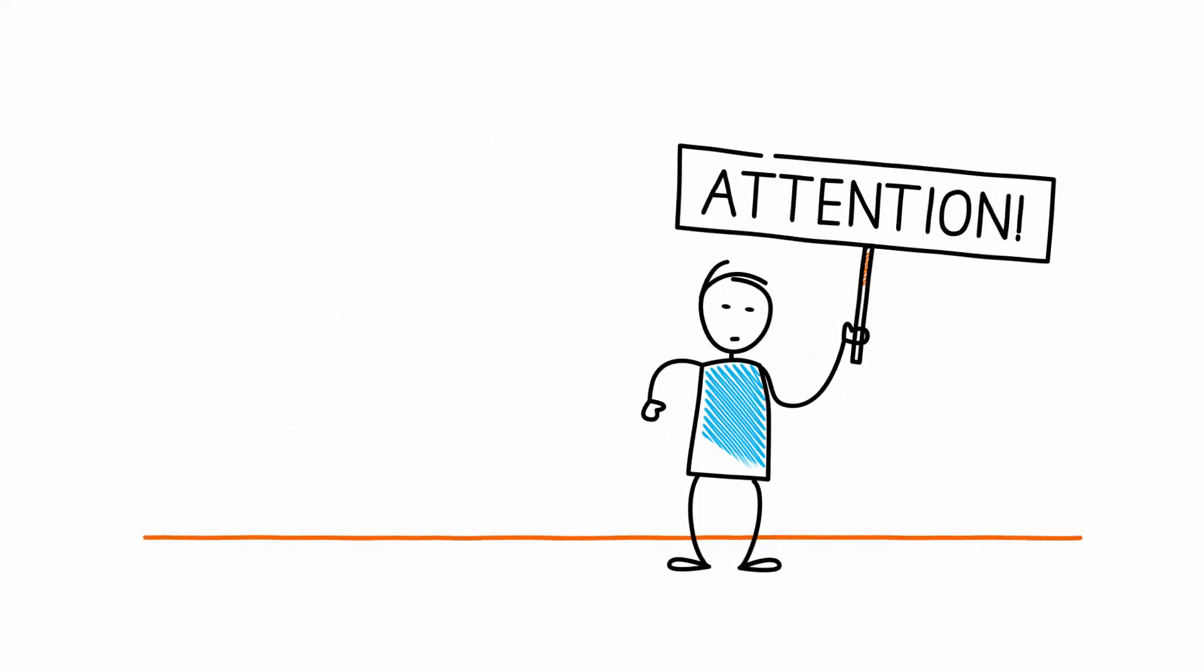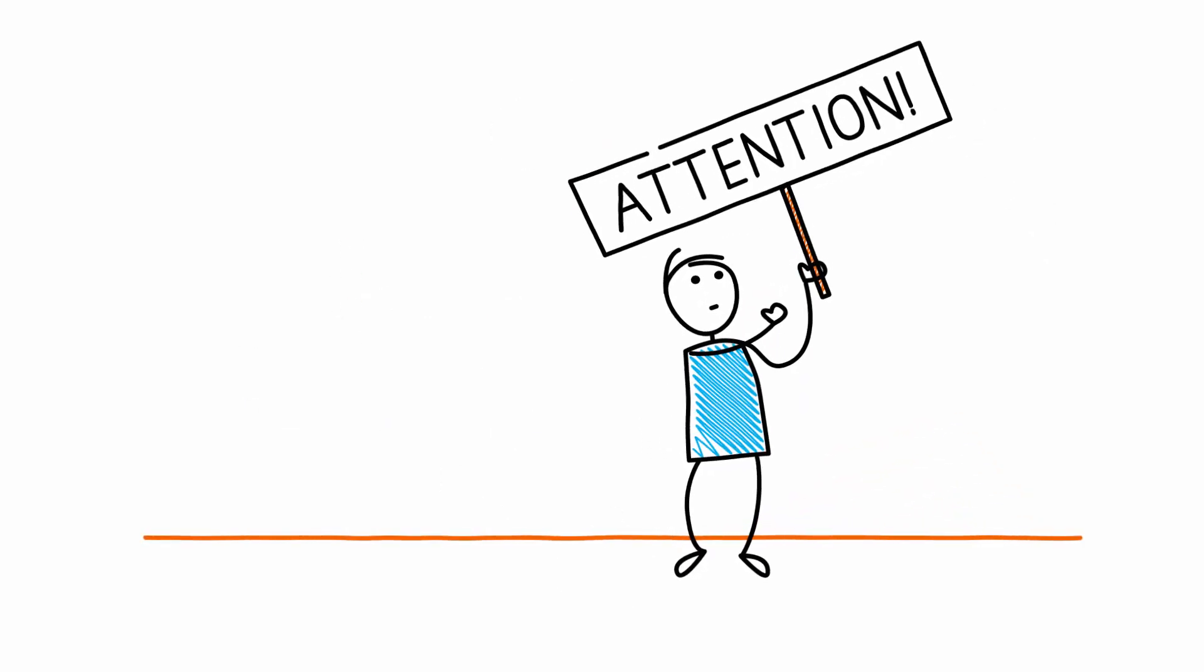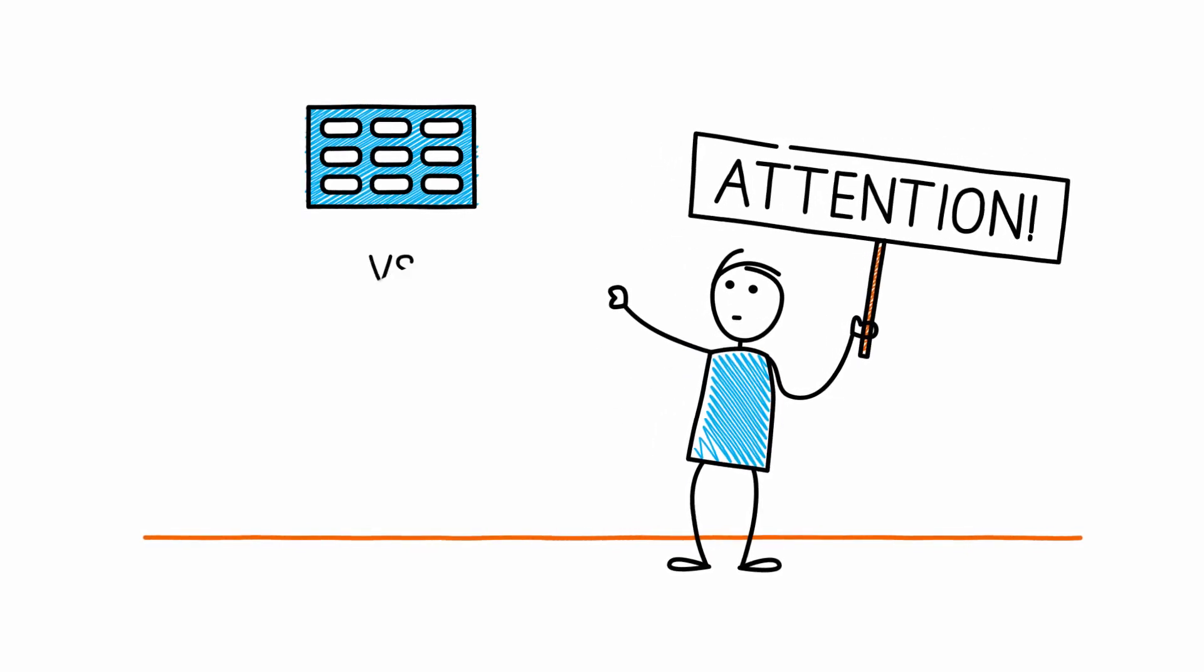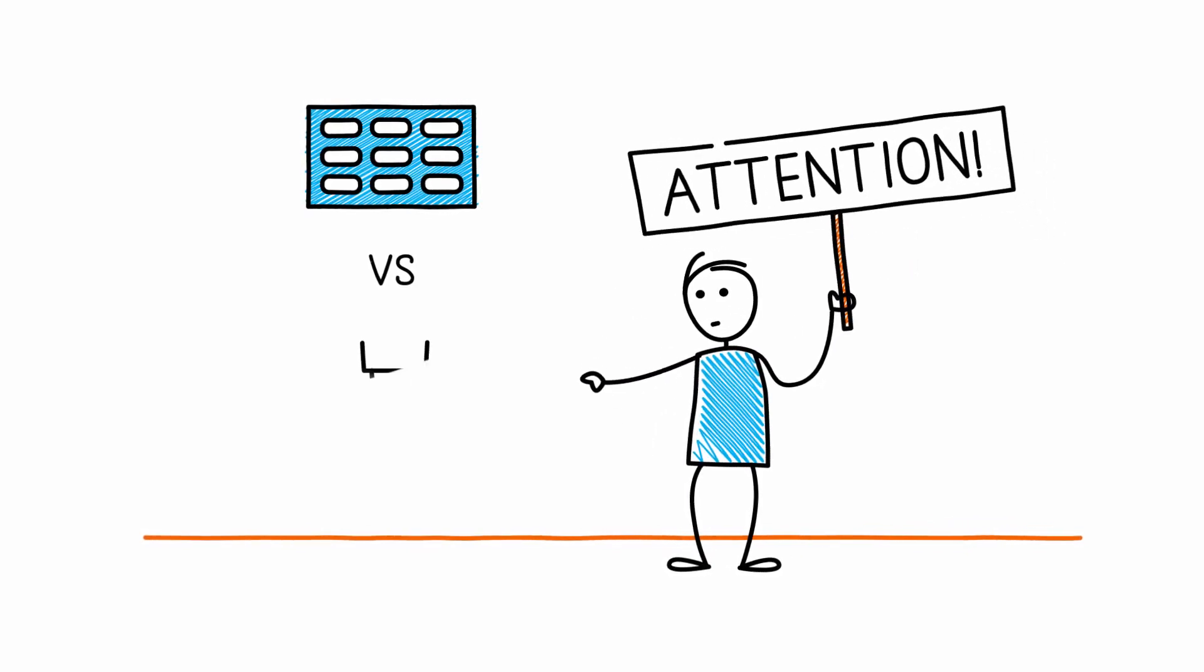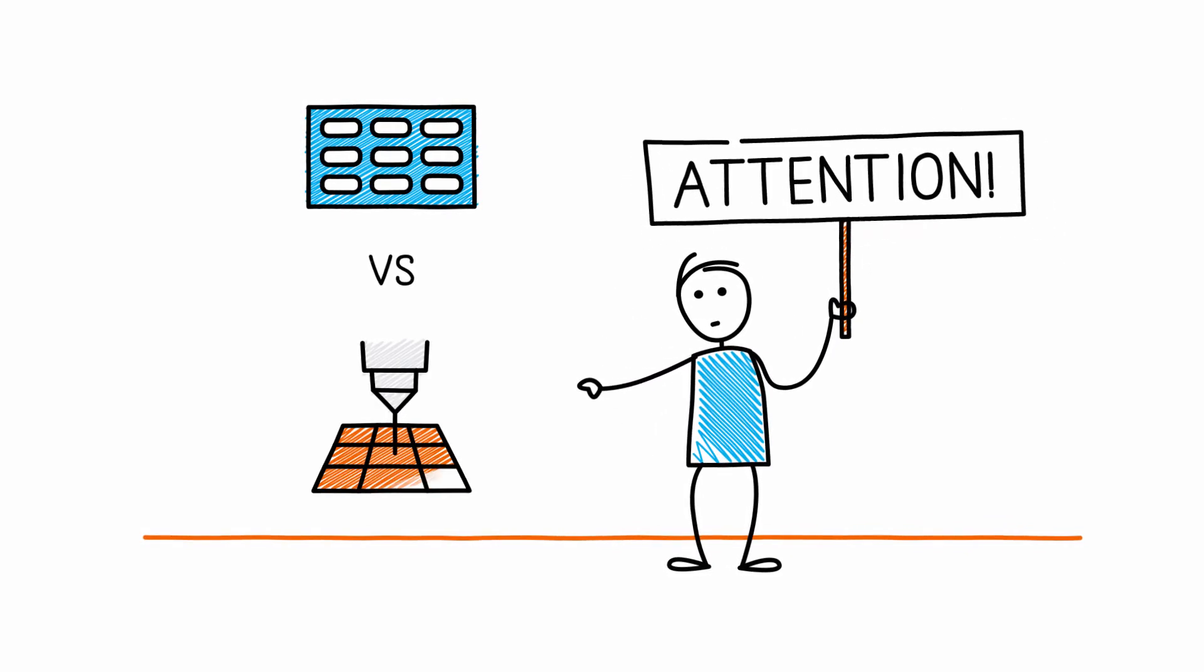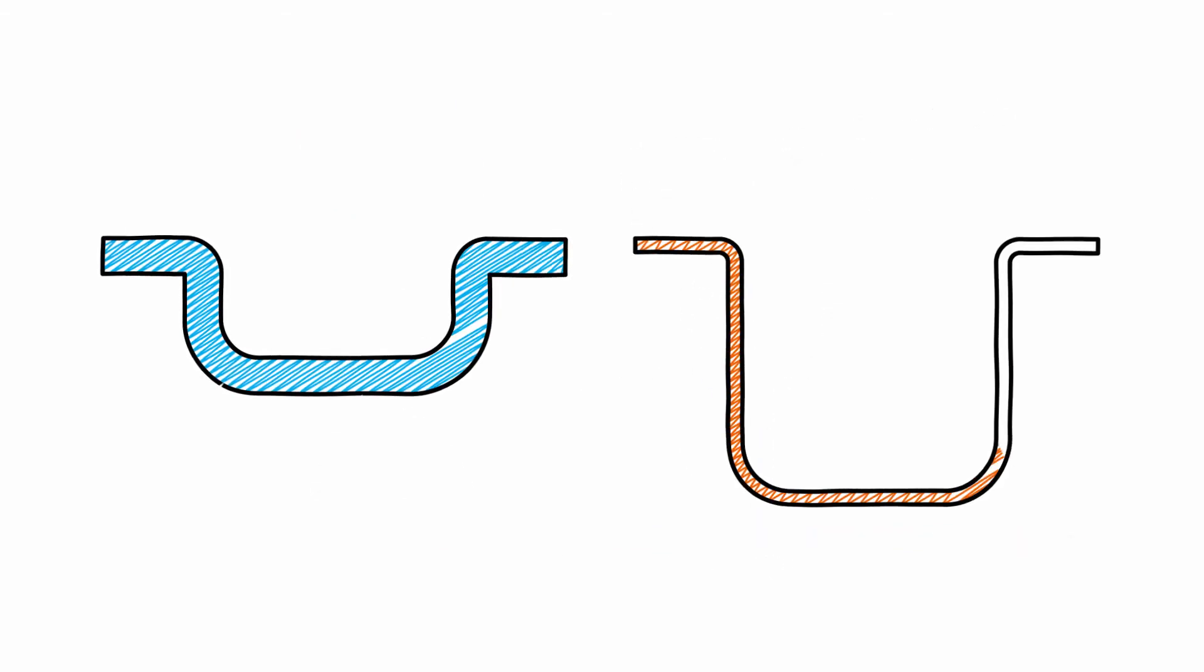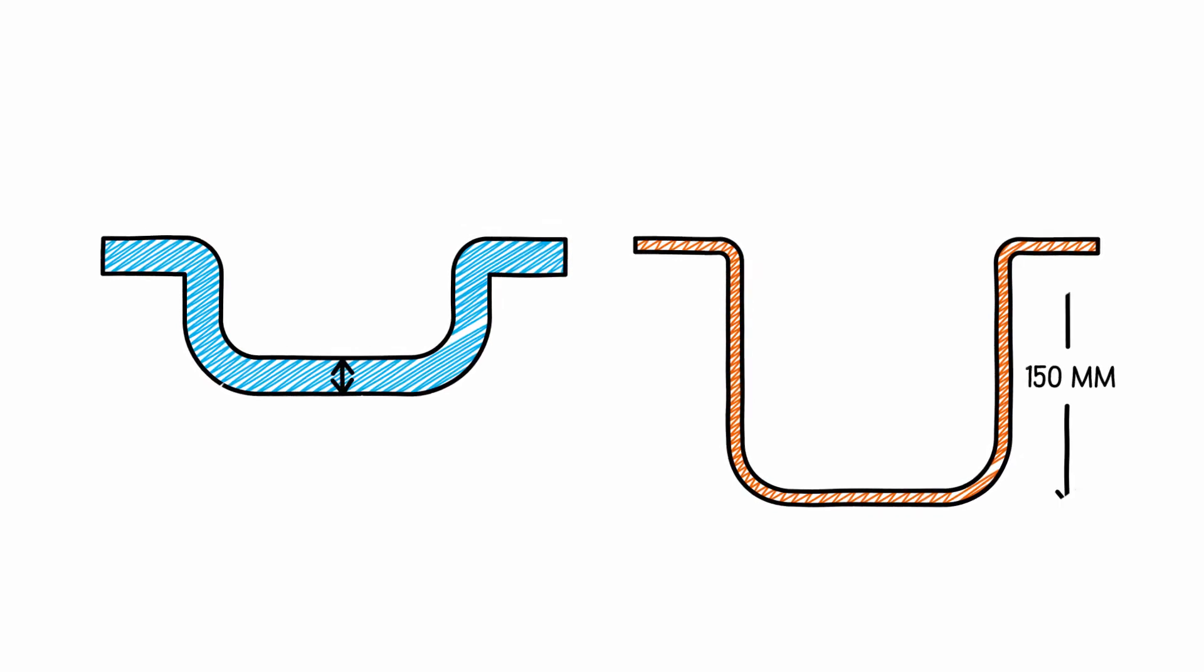There are fundamental differences between working with thermoforming and working with injection moulding. The deeper the form, the further we have to stretch the film. The wall thickness is therefore dependent on the height of your product. We offer a maximum height of 150 millimeters.